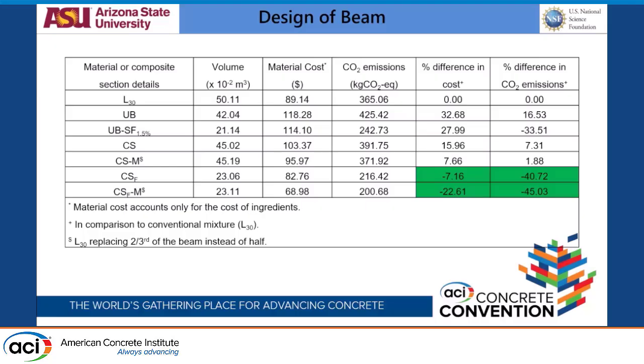So this shows that you could take advantage of a layering system, where you can put different materials in different layers to get more beneficial, more cost effective, and more sustainable sections. How would this not be possible in a cast system? Because in a cast system, you will have cold joint kind of effects when you are trying to create two different mixes, if you wait long enough. And if you don't wait long enough, you'll have intermixing, because you'll have to basically dry rod or vibrate it. You'll have an intermixing effect, and you might not get as significant a contribution as we are seeing here.